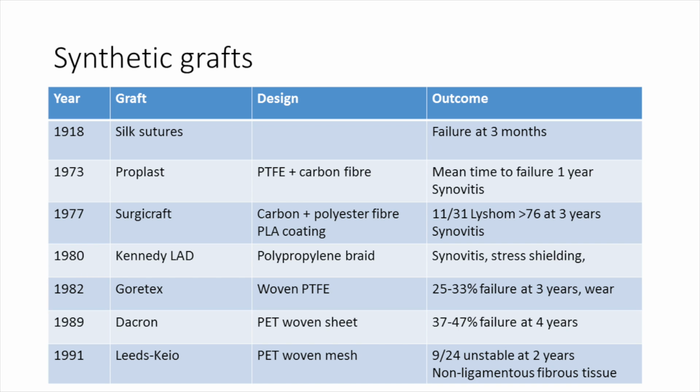Synthetic grafts have a pretty checkered history. They were first tried as far back as 1918 with some silk sutures, but they all failed. In the 1970s and early 80s, carbon fiber grafts became popular. Again, they almost all failed and led in particular to a lot of synovitis. As these grafts broke down, they generated carbon wear particles, which caused effusions in these patients.